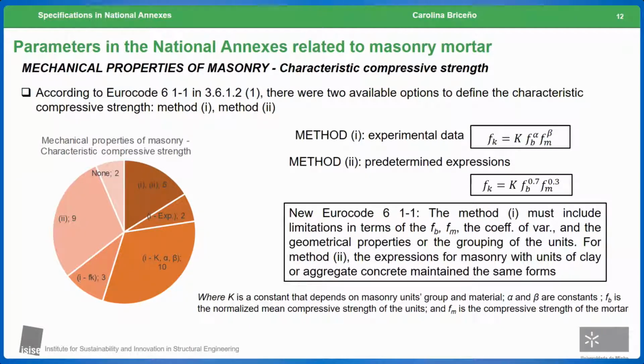I would like to place emphasis on the constant beta, which in the majority of the cases is 0.3. This constant beta directly affects the compressive strength of the mortar, which means that it affects the participation of the mortar over the characteristic compressive strength of the masonry. In the majority of the cases, as I said, this value is 0.3, but there are countries like Belgium, Luxembourg, Finland, Austria, and also the Netherlands that consider a decrease of 17% for this value. And even in the case of Estonia, the value of beta is considered as 0.